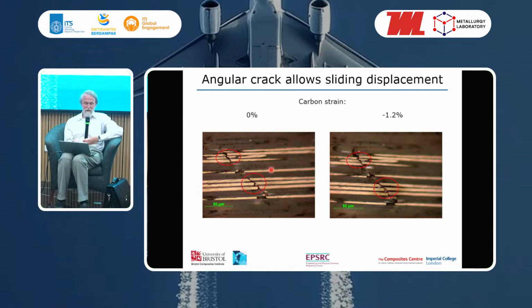And some very nice images here under the microscope show what's happening. This is the unloaded specimen after it's been initially loaded, then unloaded, and this is reloaded up to 1.2% strain. If you look at this bottom area here, you can see there's a break in the fiber, so these yellow parts here are individual carbon fibers. In this case we've got about 3 fibers through this ply. So you can see the individual carbon fibers are broken at an angle, and this angle actually goes through the whole of the specimen. But if you look at this place here, you'll see that these fragments are roughly in line. But if you come over here, you see that they're actually slightly displaced sideways.